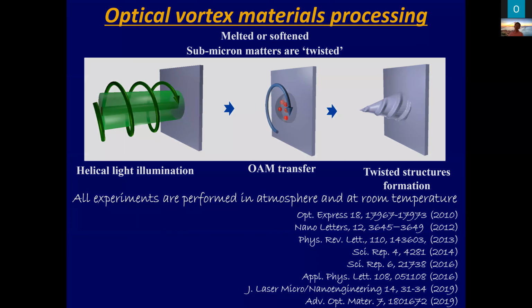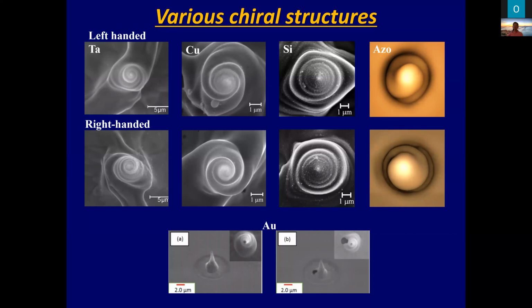I would like to show you several unique features. This is tantalum, this is copper, silicon, polymer, gold thin film. All materials are twisted at some micron scale. Quite beautiful. And of course, the twisted direction of the structured matter can be controlled directly by switching the handedness of the light source itself. Right-handed optical vortex, like a Laguerre-Gaussian mode, creates right-handed structured matter. Left-handed creates left-handed structured matter. Quite interesting that we can distinguish the handedness of the structured matter 100%.